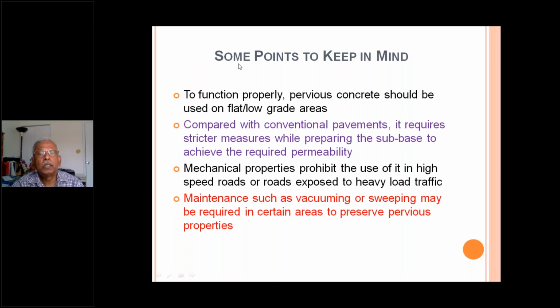Of course, when you are using pervious concrete, for it to function properly, it should be used on flat, low-grade areas. Compared with conventional pavements, it requires stricter measures while preparing the subbase to achieve the required permeability. Mechanical properties prohibit the use of it in high-speed roads or roads exposed to heavy load traffic, which I already told you. Maintenance such as vacuuming or sweeping may be required in certain areas to preserve the pervious properties.